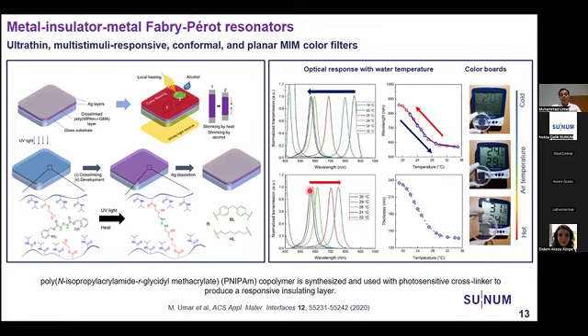If we repeat the experiment and change the water temperature slowly from higher to lower temperature, the resonance also goes to a higher wavelength. This is because of the properties of the polymer we utilized. And by simulation we show how the thickness of the polymer changes with the increase in temperature.